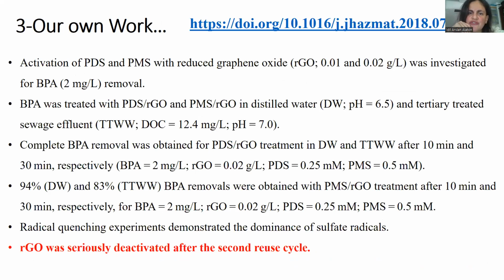Okay, this is another study. We have reduced graphene oxide that we use for activation of PDS and PMS for the removal of bisphenol A, 2 milligrams per liter. So it was treated in distilled water. We have different water media, tertiary treated sewage effluent. You see here the DOC is given, and here we work at around neutral pH, pH 7. The catalyst concentration is low. The oxidant peroxide concentrations are quite feasible. And we have, again, good removals, high removal efficiencies of bisphenol A. We have a radical quenching test that demonstrated the dominance of sulfate radicals here.